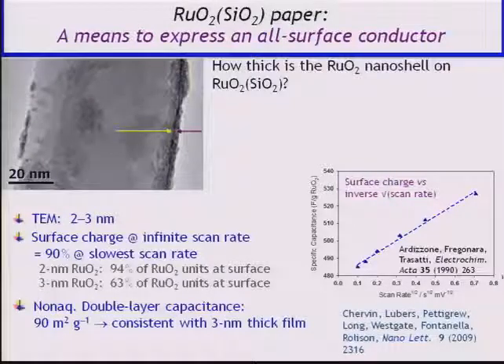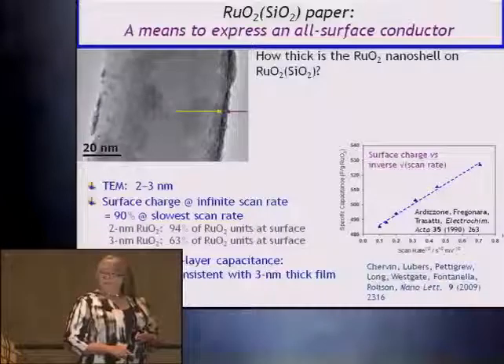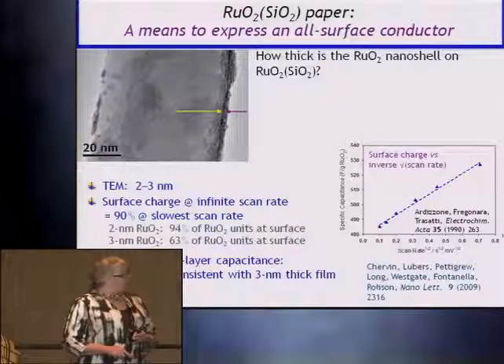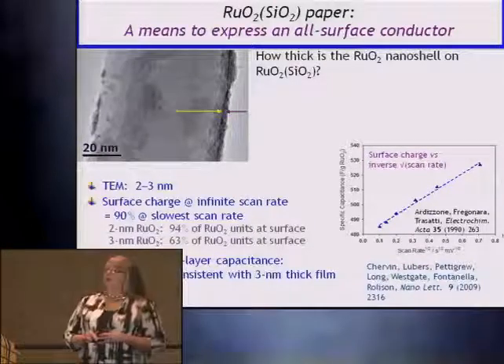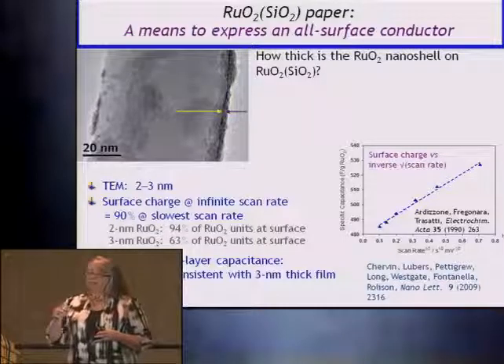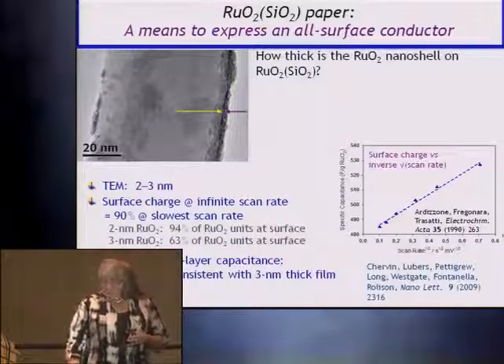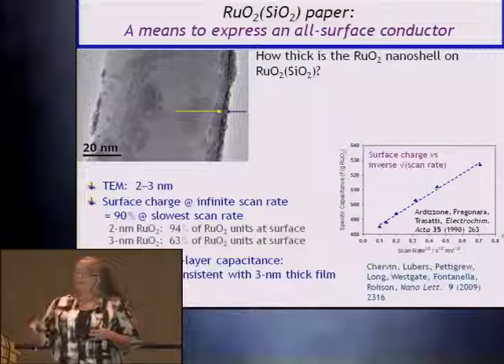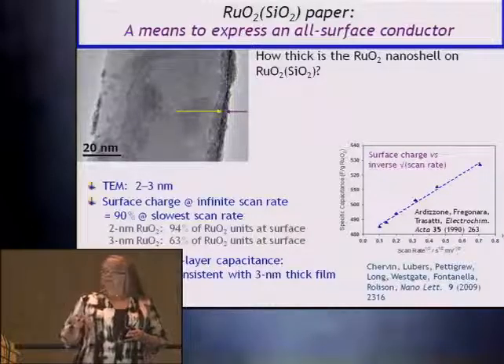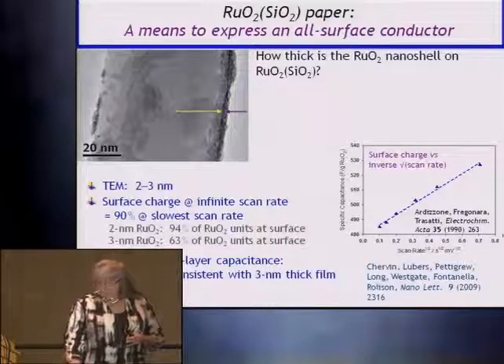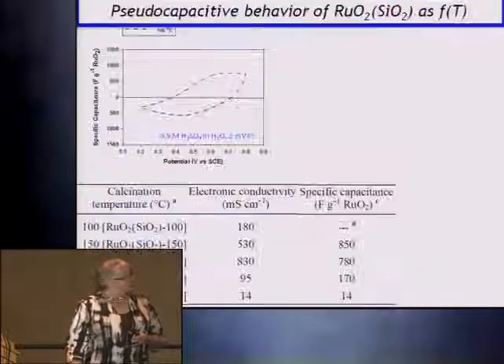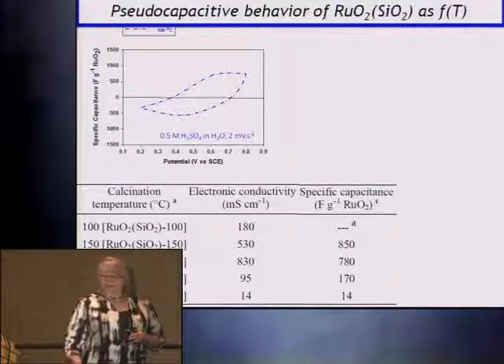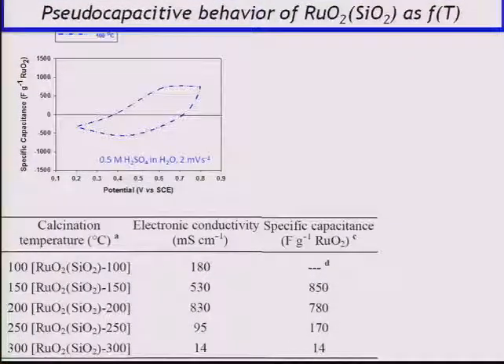And when we go into a non-aqueous electrolyte where we can't insert protons, use something like tetrabutylammonium perchlorate, then we back out 90 square meters per gram for that ruthenia, again putting it in about a 3 nanometer thickness range. So an extremely limited amount of ruthenia is giving us some really nice properties with respect to the electrochemistry and charge storage. So let's look at its charge storage as a function of that heating curve I talked about.